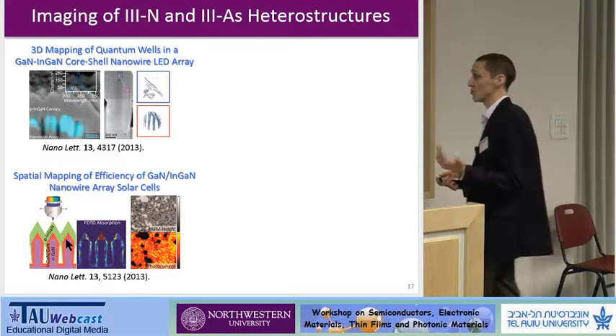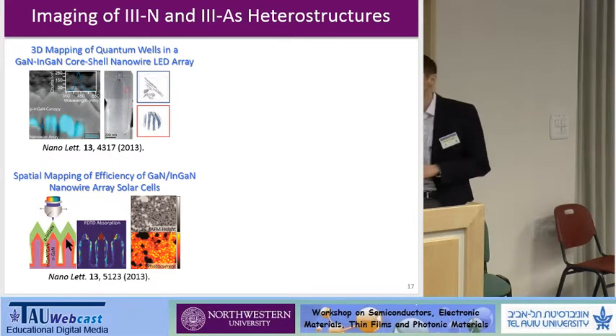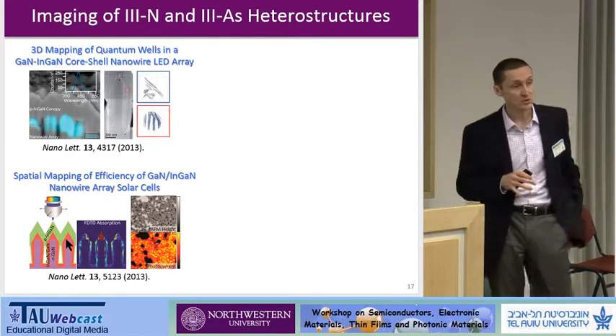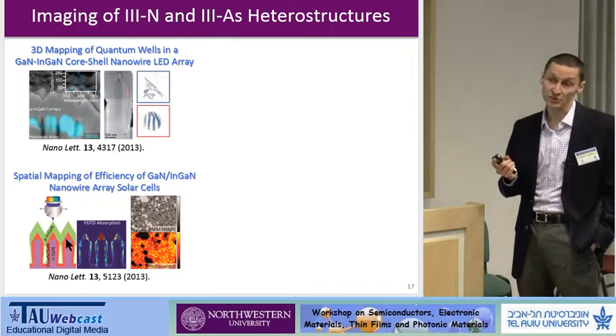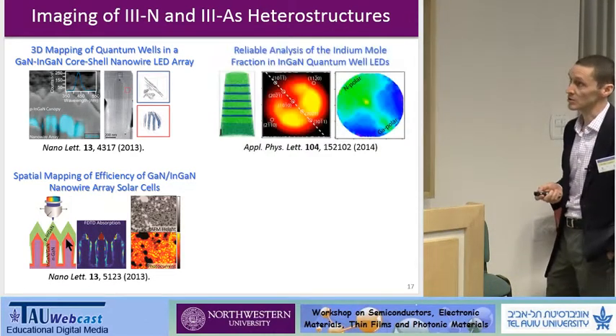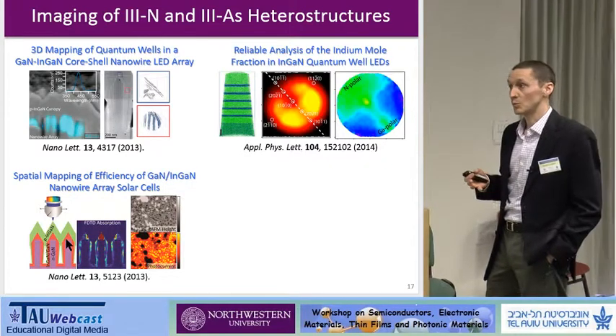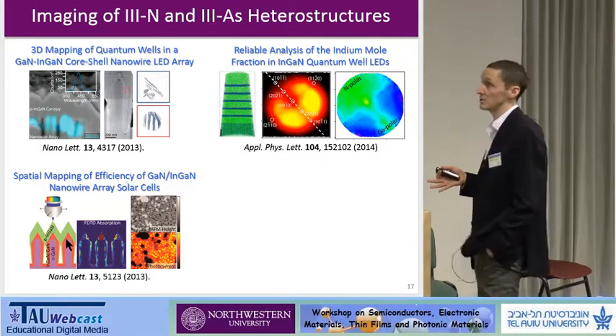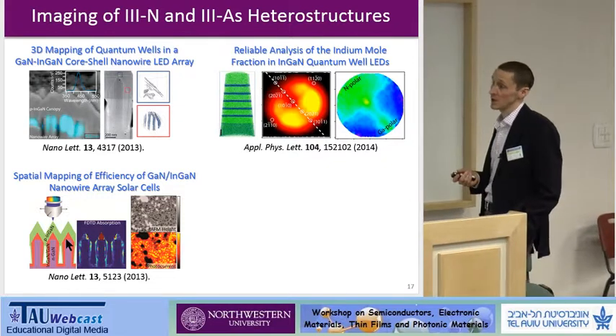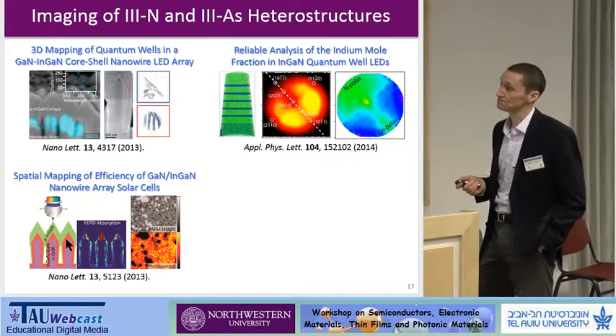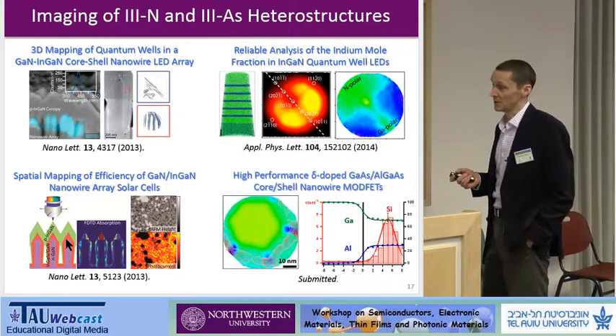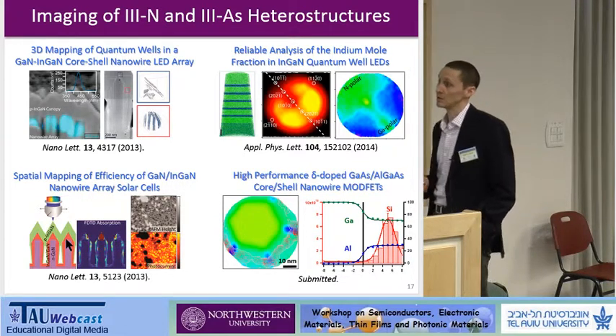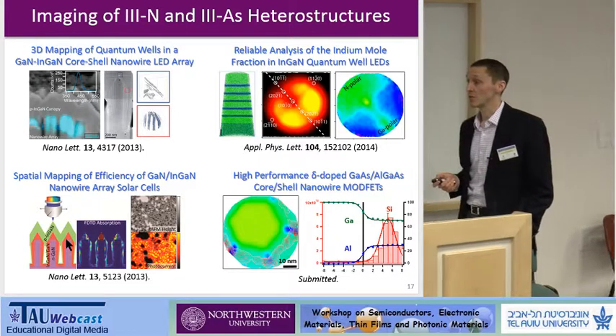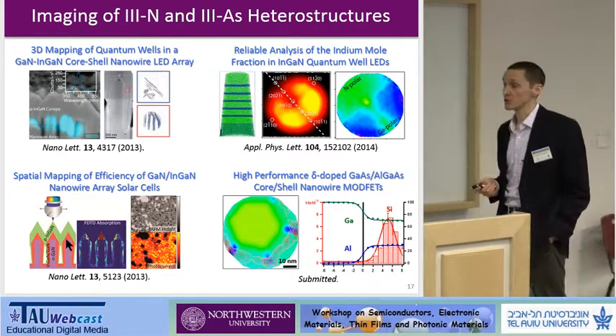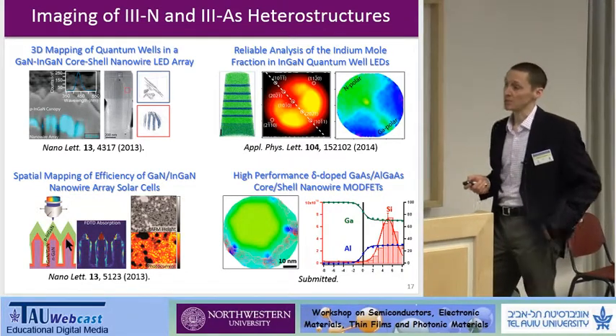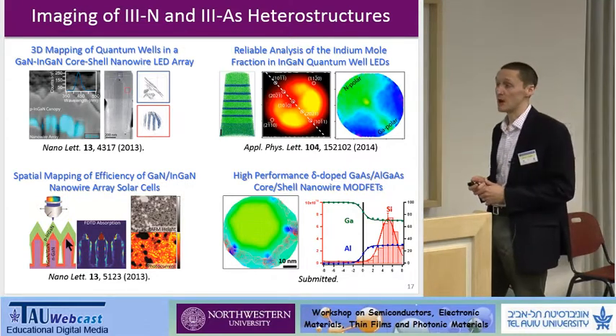We also ran these as solar cells and used the photocurrent mapping to essentially spatially map quantum efficiency and understand how that related to the photonic structure as well as the electronic structure. We've done some analysis on more conventional planar InGaN LEDs with collaborators at Rensselaer Polytechnic Institute. And then finally, more recent unpublished work on III-arsenide nanowires, where the interest there is in high-performance transistors, and we're using atom probe to analyze the delta doping in MODFET structures.